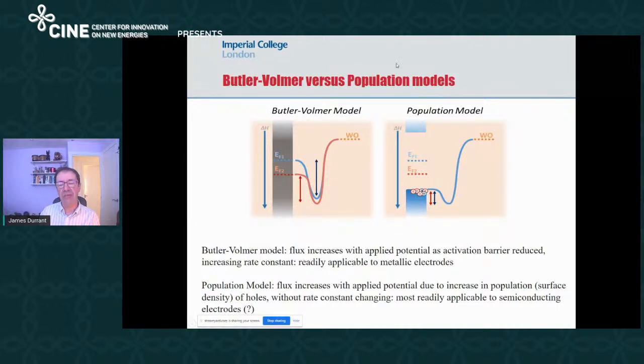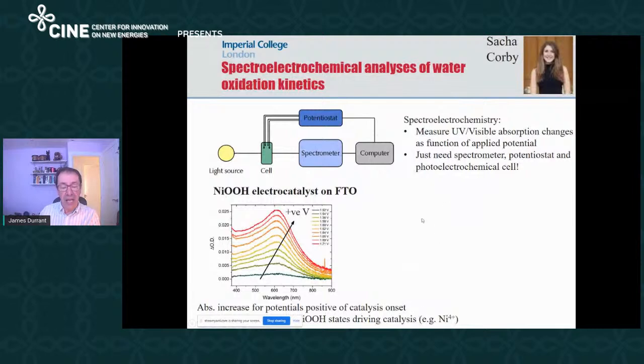We were interested in thinking about whether a population model might work, and in particular whether a population model might help us understand how we bring 4 holes together to drive the kinetics of water oxidation. Now, in order to measure this, it turns out it's actually rather easy to do spectroscopy to measure these kinetics. And here's an example, actually not of a light-driven reaction, but water oxidation on nickel oxyhydroxide electrocatalysts, which is a very interesting material for electrolysis for water oxidation.